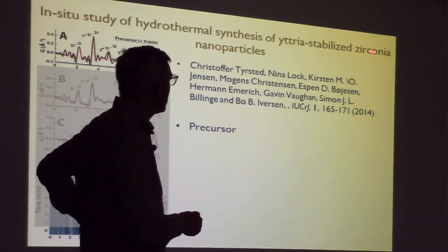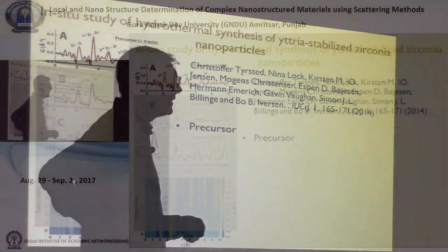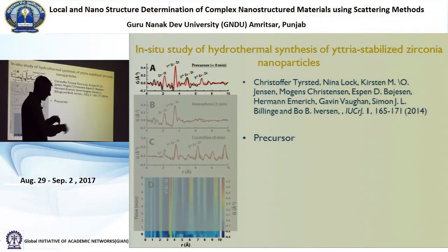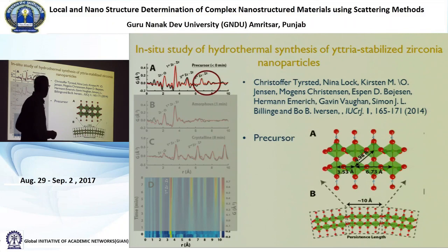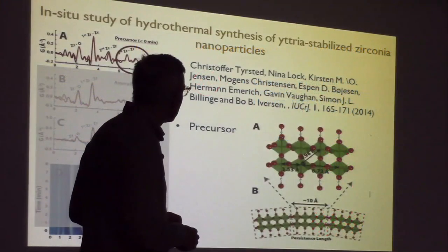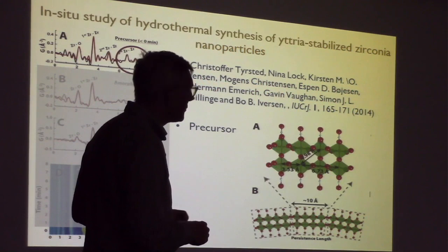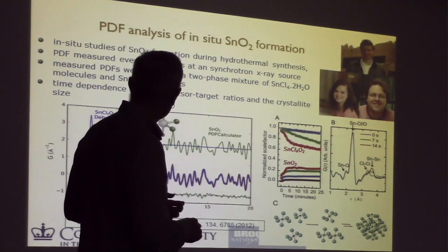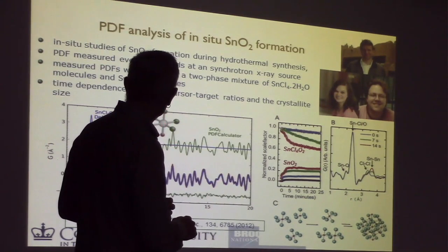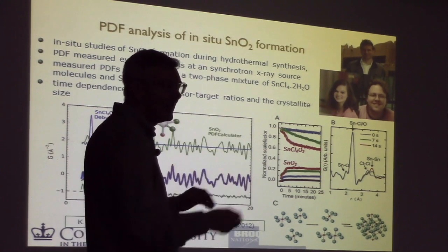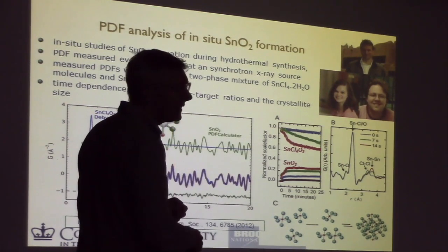In the case of yttria-stabilized zirconia, it was even more interesting. So you take the reagents and you dissolve them in the water. And what happens in that case is that, again, it's this metal ion in the middle of an octahedron, and the metal ion is the zirconium. But it doesn't just float around like a single octahedron. So in this one, you had a peak here, which was this center to the edge, and a peak here, which is the edge to the edge, and that's it. You only have two peaks because it's a single octahedron.